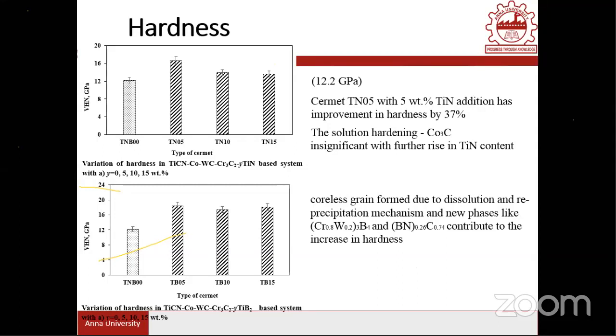And the TiB2 addition, the second bar chart shows the TiB2 addition. And it shows really a good improvement. Even for 5% nano TiB2 addition, because of the formation of these phases in the microstructure, the value goes to 19.1 GPa. And after that, even if you add 10%, 15%, the value is constant. It is fluctuating between 18.5 and 19.1 within that range. That means it doesn't have any other significant effect after 5% addition. That means a 5% addition of nano TiB2 improved the hardness value tremendously.